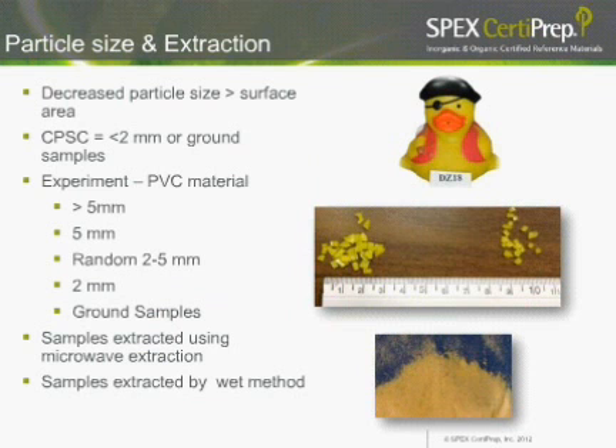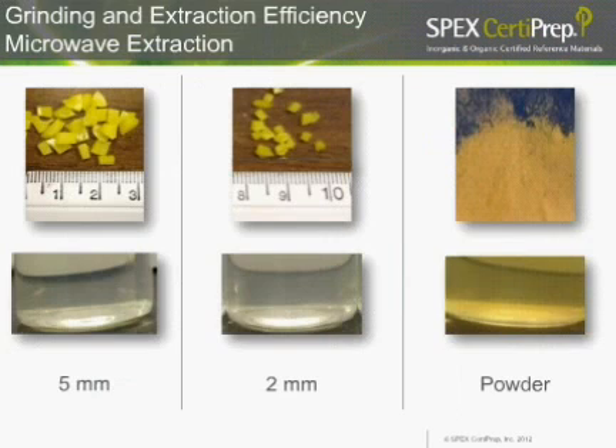We used 2 methods of extraction. We used a microwave extraction method, since we do have a CEM microwave on our premises. We also used the Consumer Product Safety Commission's THF extraction method. What we found is that the 5 millimeter parts, when put in the microwave extraction method, produced a somewhat clear, almost white extract, so it didn't really seem to have a lot of color. The 2 millimeter extract was slightly hazier with a slight tinge of yellow, but the powder really made the most dramatic difference in the microwave. We had a very dark yellow colored sample.